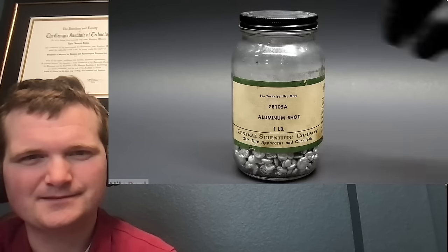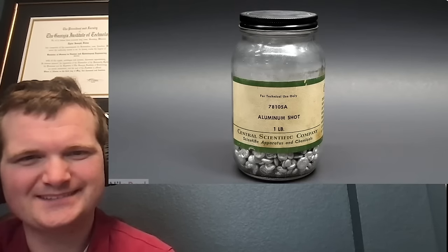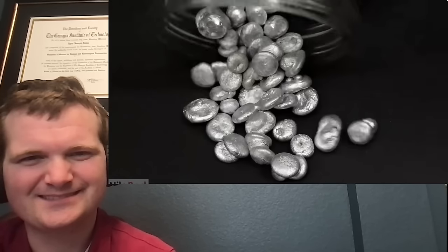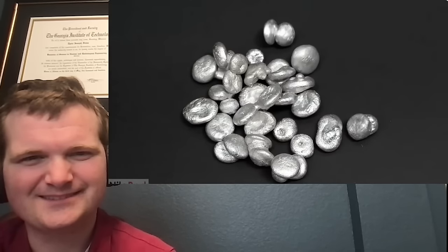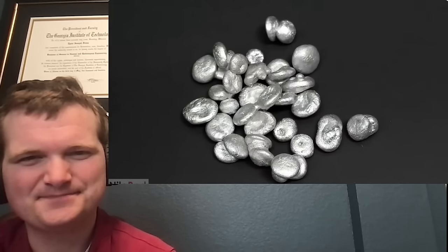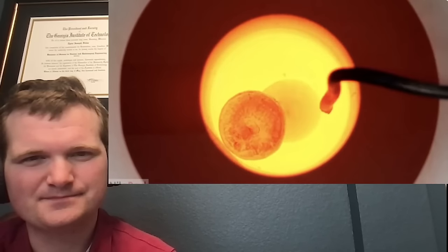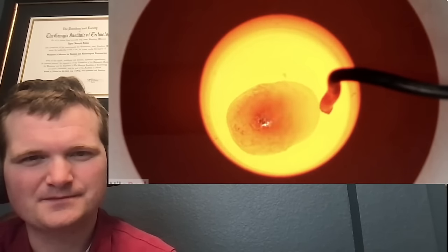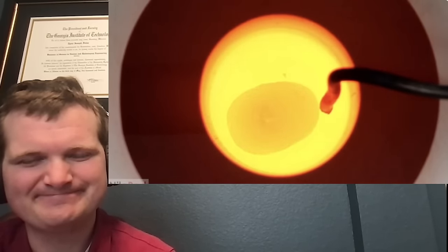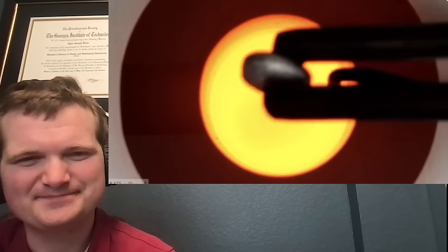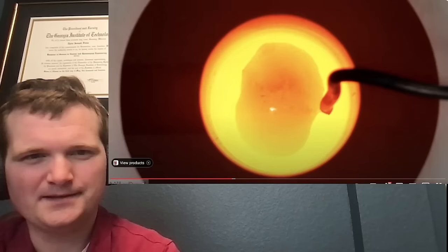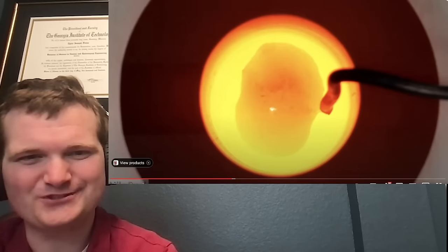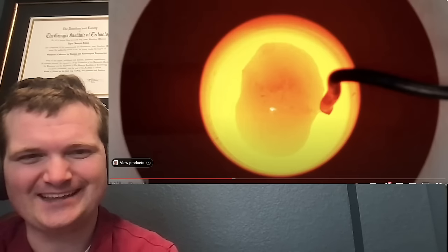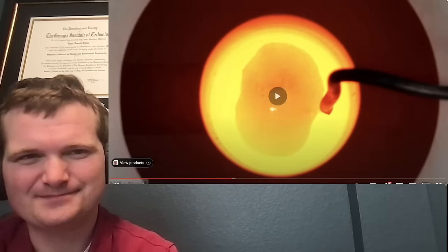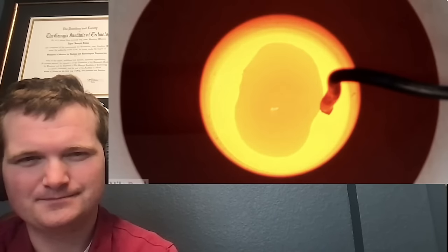This time, though, I decided to use some much larger pieces which weren't quite as pure, but I was hoping that they would liquefy a lot more easily than the smaller ones. To load it in, I just carefully dropped in the first piece, and I was very happy to see it all quickly combined with the gold. I then added the rest of the aluminum, which also quickly got sucked up. Yeah, the melting point of aluminum is about half that temperature, so not surprised. It did not last very long. At this point, it was already looking way better than the first attempt.